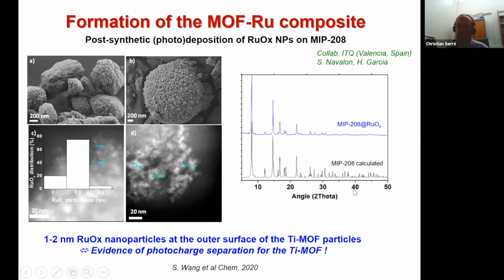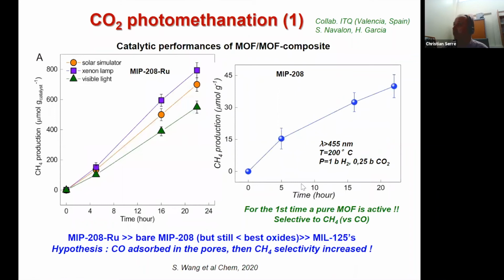Of course, this was not only done to demonstrate that this material was photoactive, but also to improve the performance for, let's say, photomethanation of CO2. So the material was shown to be stable also after this reduction. And what they did is they tried under visible light, 200 degrees C, 1 bar of hydrogen, 0.25 bar of CO2, the photomethanation of CO2 with the pure MOF. So far, there was no report that a pure MOF could be active for such a reaction. And in this case, the yield was not exceptional, but was the first evidence that the pure MOF could be active for such a demanding reaction.